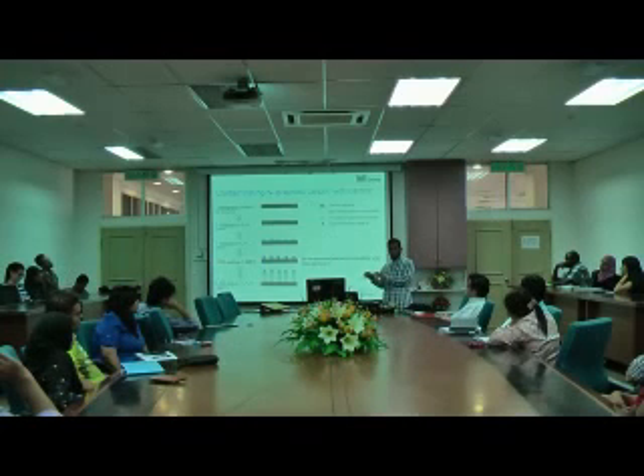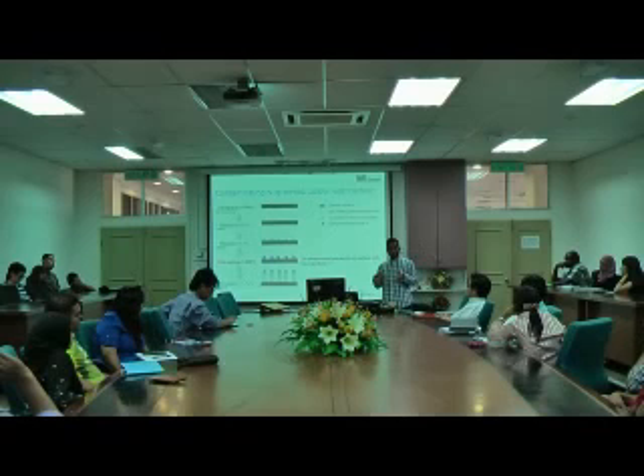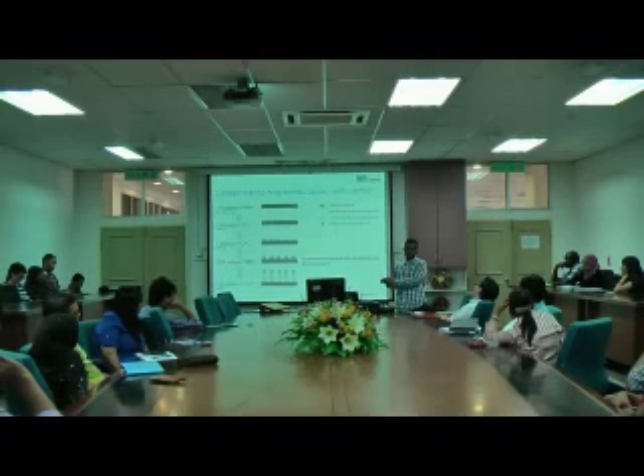See, if I do this with copper at a certain condition, I may be able to burn it out. But the condition is difficult. It will not be easy to observe as it is. This is my approach to this. If you want to prove something, the experimental design would be that the effect that you put in needs to be significant enough to be observed. There might be similar behavior with zinc or copper, but the effect would not be so significant. I would then need to put more effort into investigating it, and that's too much time. With nickel, it's just the best system. It's reactive enough. It grows nanotubes. It's easy to observe.